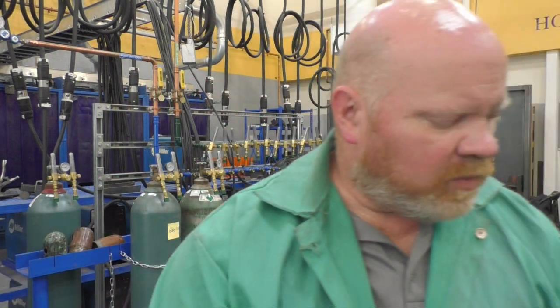The other plate, again, as I said, was welded with short circuit transfer .023 wire. I don't know what the amperage was. I didn't look at the machine, but 21 volts and 500 inches per minute. It was hot enough that it passed the break test on 3/8 plate.